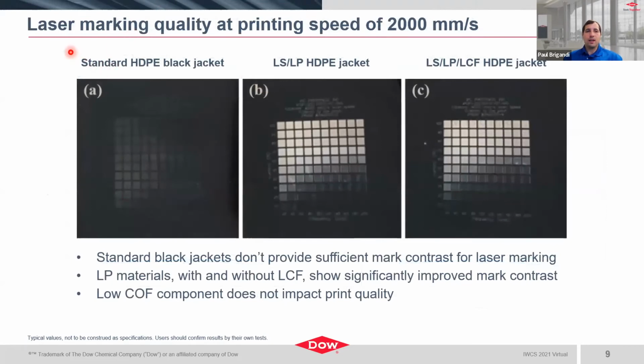Now we'll look at laser marking. So what we've done here is actually sent some materials out to be laser marked. And that's what you see here. These are compression molded plaque specimens here, where we've looked at the standard HDPE jacket, the laser print low shrink, and the laser print low shrink, low COF jacket.